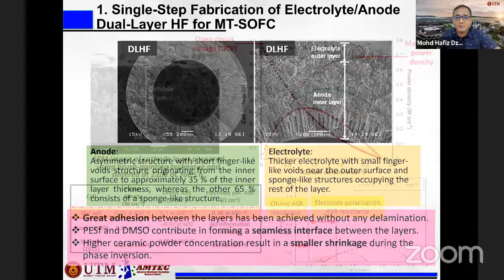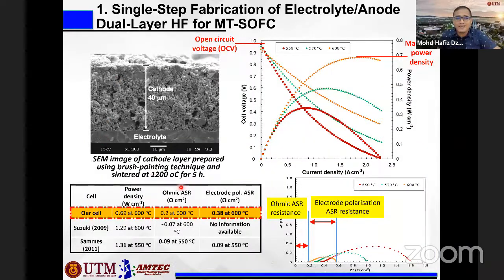So from the dual layer, in order to get the data for the complete fuel cell, we have to add the cathode layer by using a brush painting technique. We do this manually, and then we sinter them at 1200. Okay. So we measure the fuel cell at temperatures from 550 to 600.